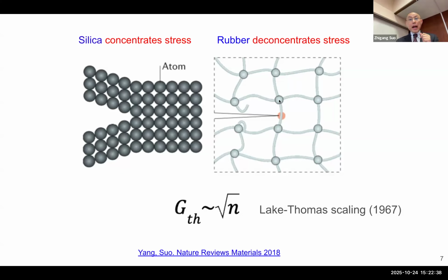Now, rubber is different. Rubber has long chains, we just said, right? There are maybe 1,000 monomers, repeat units, along a single strand. Now, when this crack comes to this strand, it tries to break a single atomic bond. You only need to break one atomic bond for this to move ahead. But before this break, the entire strand is under high tension. Why? Because between two strands, the interaction is non-covalent, it's very weak. So that high tension is able to transmit over a long distance along the entire strand, right? So when you break a single atomic bond, a covalent bond, the entire strand's energy is dissipated. That's why it's so much tougher.